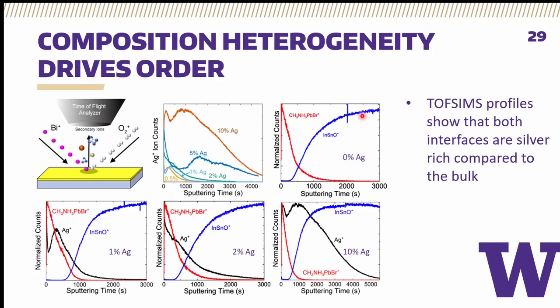Yes, silicon bromide, that's right, with the same molar mass as silver, which complicates the spectrum. But we tracked 3 different species. We tracked methyl ammonium lead bromide, indium tin oxide, and silver as well. And we saw, amazingly, for each of these thin films, that at the interface of the